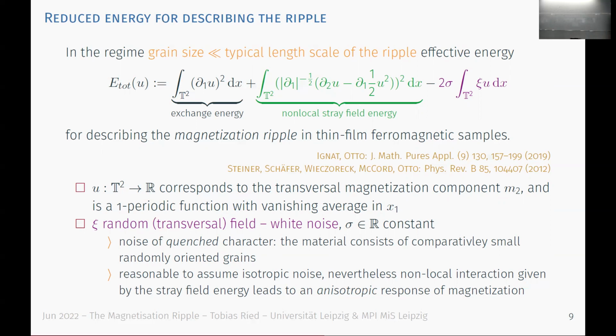Then what survives effectively of the exchange energy is a d1U squared. So variations in the one direction are still somehow suppressed by this energy here, a harmonic energy in one direction. Then due to going to a thin film limit and working out Maxwell's equations, looking at oscillations around 1, the non-local stray field energy can be written as somehow a negative fractional derivative in the one direction of this combination, which basically comes from expanding the square root.